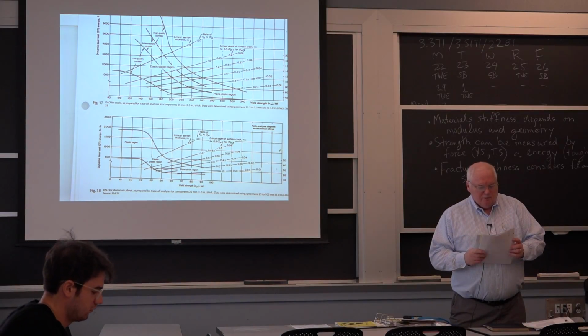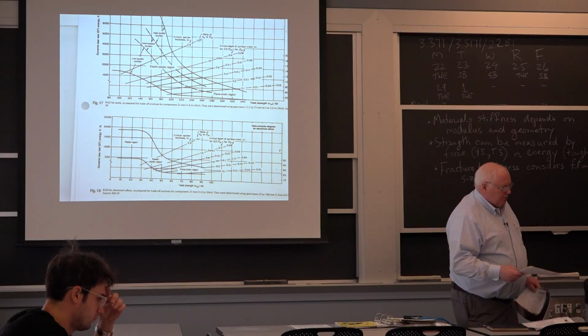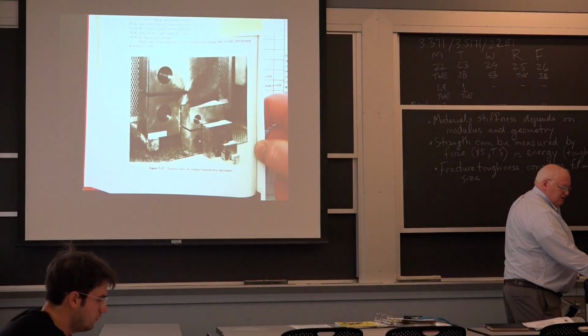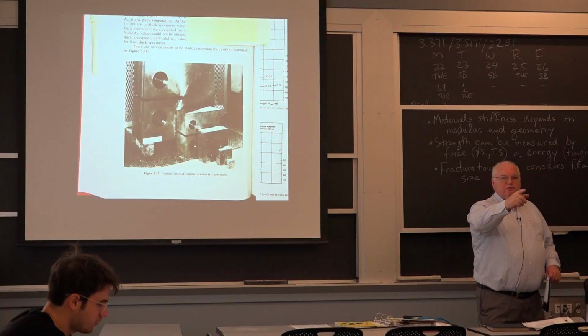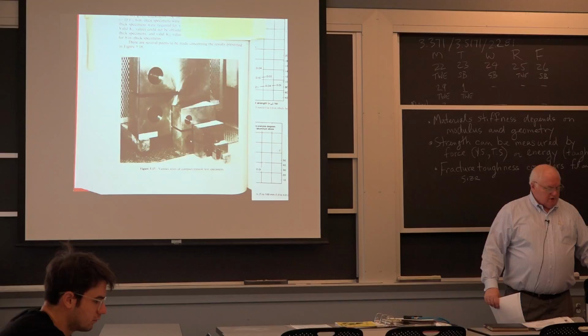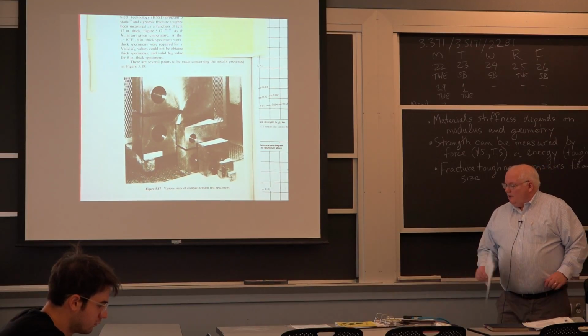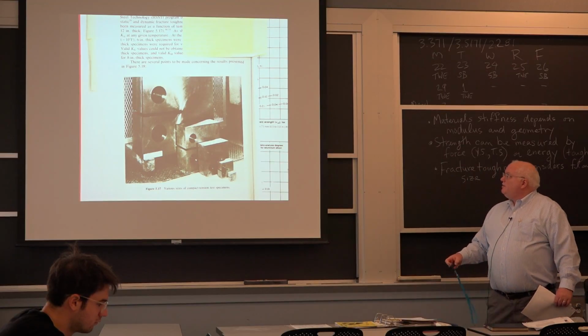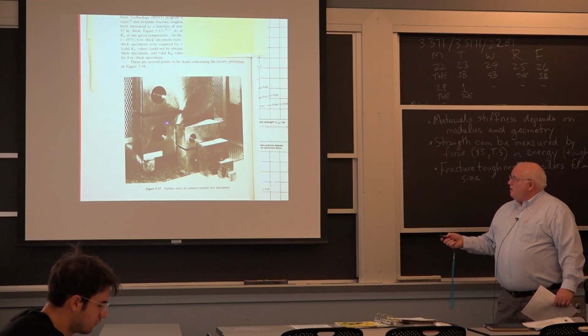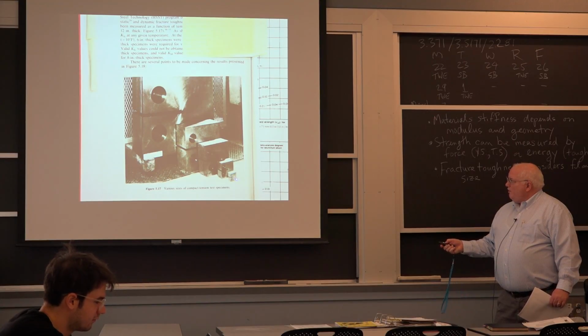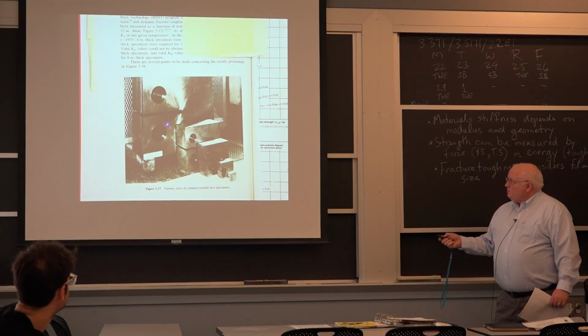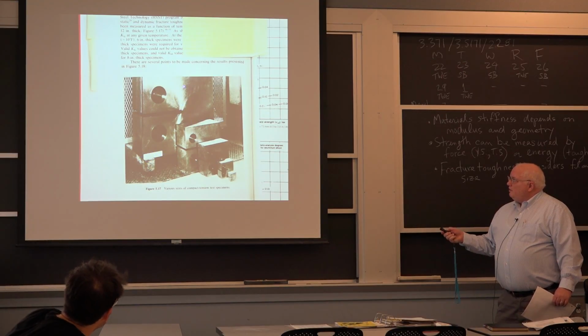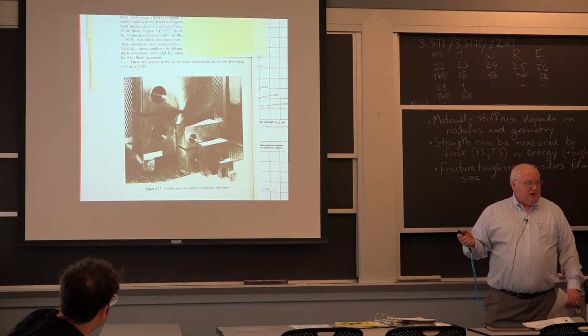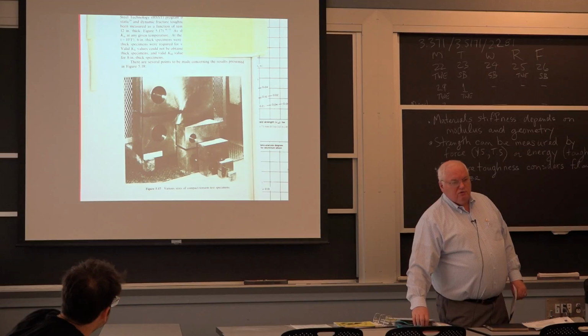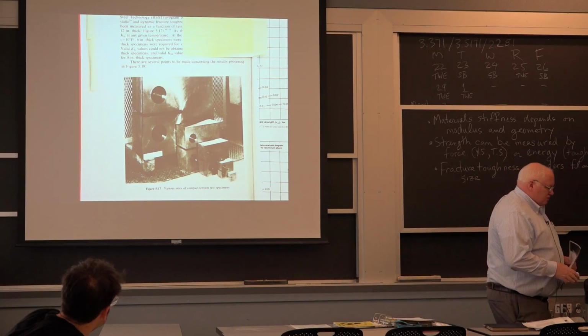specimens. If you go back to a book by a couple of guys at U.S. Steel, back from the 1960s when they started doing fracture toughness specimens, I passed around that little piece of granite. That's the fracture toughness specimen. These are fracture toughness specimens. They're called compact tension specimens. And there's the holes that you grab the thing in a great big machine. Here's a little one that's actually probably larger than my granite one. And you get bigger and bigger and bigger until here's one sitting on a couple of 4x4s here in the lab. This one weighs tons, okay? Turns out you need to know how thick your steel is in order to measure the fracture toughness of the steel. And we'll go over some of that in a little bit here.